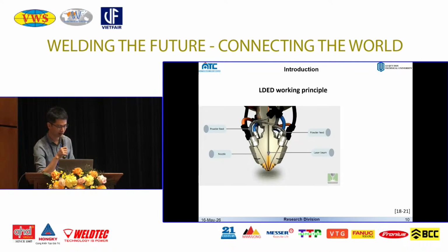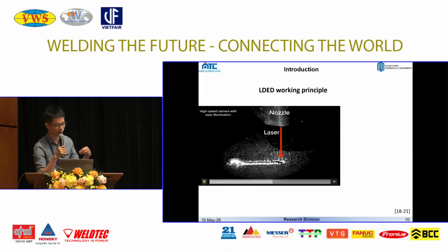Let's see how LDED works. I have a video here, so hopefully it can run well. We have a focused laser beam hitting a small area of the substrate, and the metal feedstock, usually powder or wire, is delivered into the molten pool. Then the material melts and solidifies quickly, and we can utilize a robot arm or CNC system to move the deposition head. Because it is a very high energy, highly focused laser beam, the process can melt almost any kind of metal and alloy, making it very promising for difficult-to-machine materials. Within our system, we succeeded in printing stainless steel, titanium, Inconel, and so on.